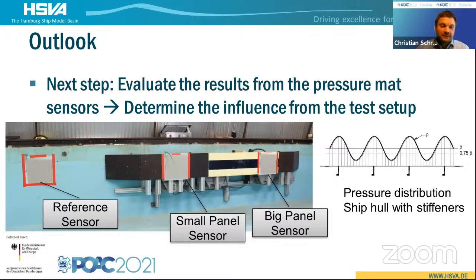So what is the outlook on the next steps we want to do? So actually we are in the phase of evaluating the local load sensors to draw a conclusion of the force levels directly on the sidewall compared to the a little bit less stiff measurement devices. And also what we plan is to try to abstract the findings a bit to pressure distributions, probably like ship hulls or something different, where of course the areas which are stiffer take much higher ice loads, for example, compared to areas where the hull bends a bit, so the force level generally is a bit lower.